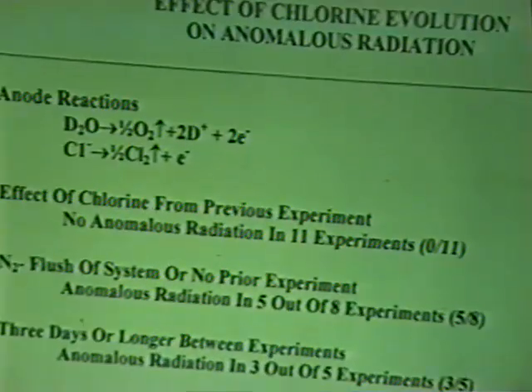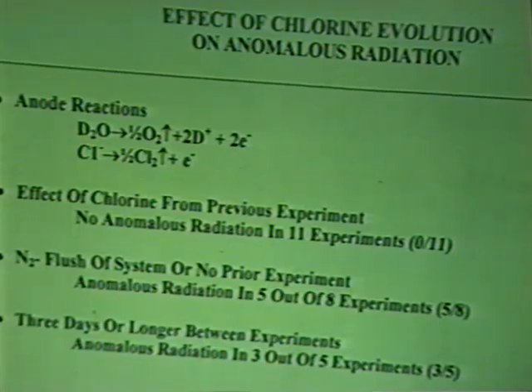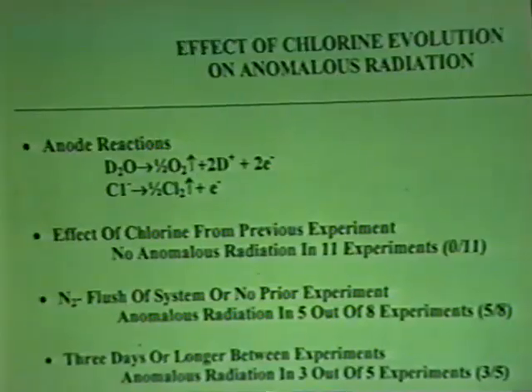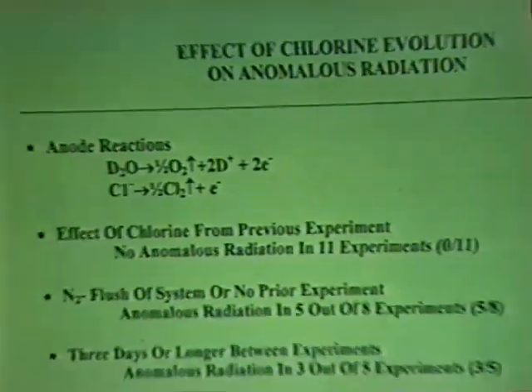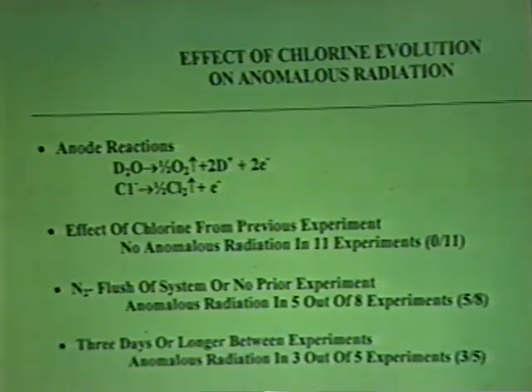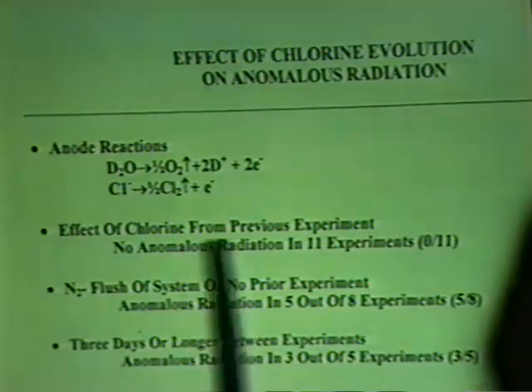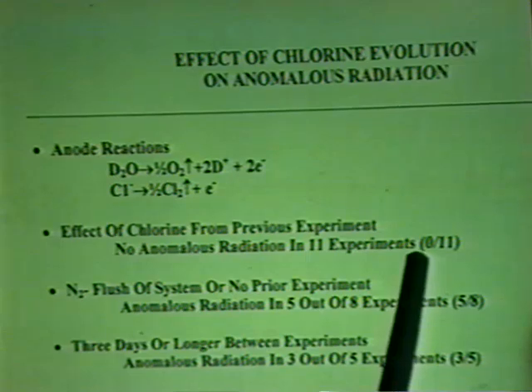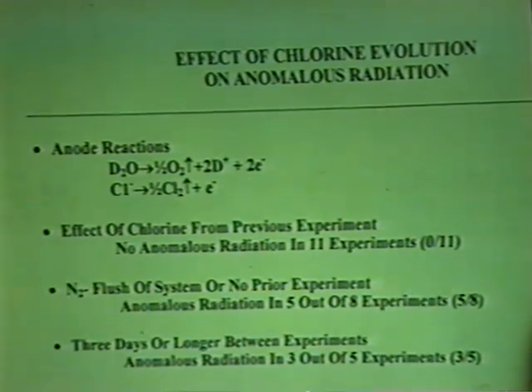Well, long after this, I finally figured out probably what the reason is. You evolve chlorine, and if you don't allow time for the chlorine to dissipate or don't flush it out, then you don't get this anomalous effect. Chlorine has some effect, I don't know what, maybe passivates the electrode or whatever, but if we did the experiment rapidly and didn't allow time for the chlorine to get cleared out, our success rate was 0 out of 11. That was when the laboratory brought this equipment in, basically.